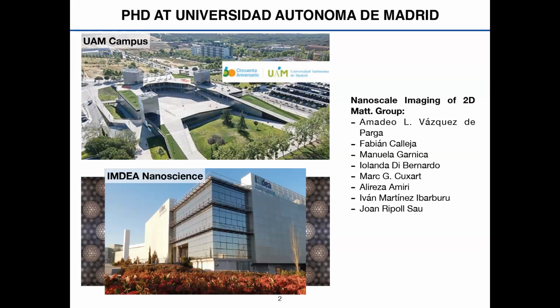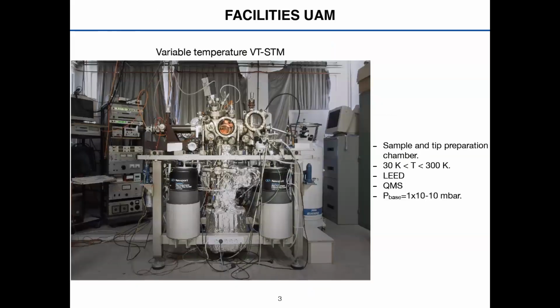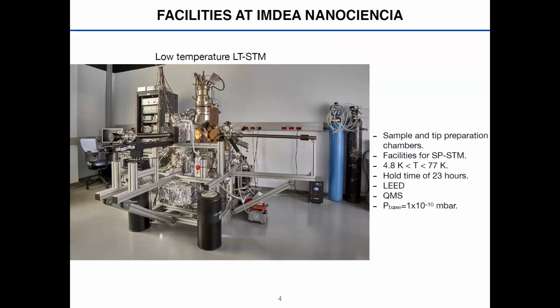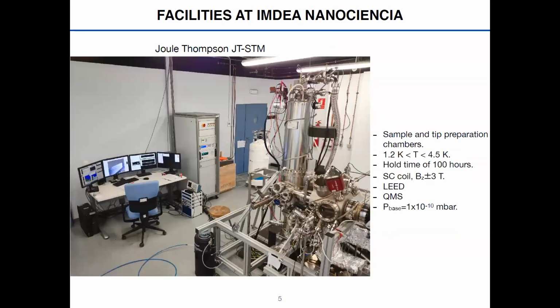Many work there with STMs, and in this case they have 3 different STMs. One works at variable temperature, between 30 Kelvin and 300 Kelvin, depending on whether you use a flux cryostat that the microscope has. And then 2 low temperature STMs. This one here is an Omicron that can go down to 4.8 Kelvin for 23 hours. And another one is this low temperature Joule-Thomson STM that can go lower in temperature, 1.2 Kelvin, for a longer period of time. It has a hold time of 100 hours.